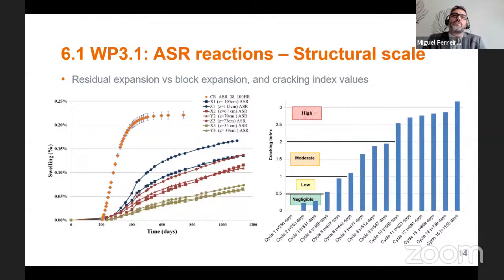And on the right, we see the macroscopic monitoring of the mockups and the use of the cracking index, and we see that this shows a constant increase even in acceleration phase, and possibly a leveling out phase towards the end there. So what data is still missing? We are still performing the residual expansion tests on the last concrete cores taken from the mockups, and these are being done, of course, at 38 degrees and 100% relative humidity. So the analysis of these results is now the next step, the next phase in the project.